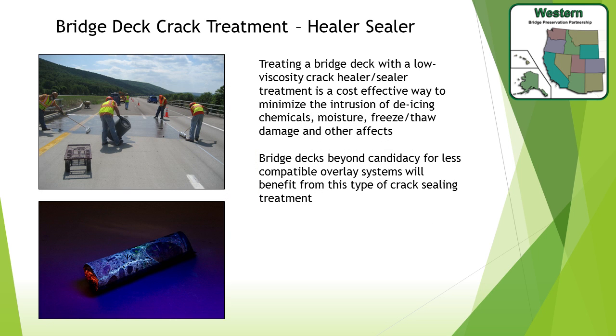There are healer sealers with two scenarios where you might want to use them. One is the New Mexico scenario — you come onto the deck, treat the cracks right away, and let the deck go through some thermal cycling. The other is when the deck is really not in good condition and you don't have the budget to replace it. It's not a good idea to put a thinner polymer overlay on there because you'll induce more stresses into a deck already in poor shape. So seal the cracks, do your patching and repairs, seal the cracks, and buy yourself a little bit of time.